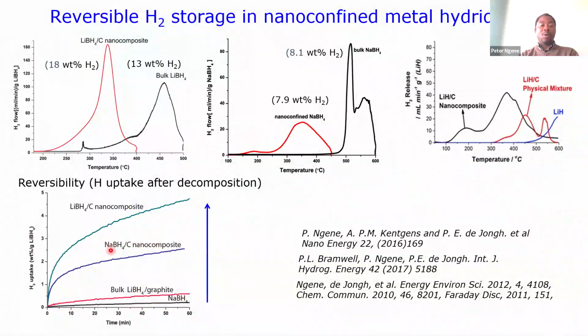Now, if you make the nanocomposite, if you just put them inside the scaffold pores, which are very small pores, between, I think, depending on the scaffold, 2 and 10 nanometers, you do see that both sodium borohydride and lithium borohydride that have been decomposed can also reabsorb hydrogen. So this is quite interesting.